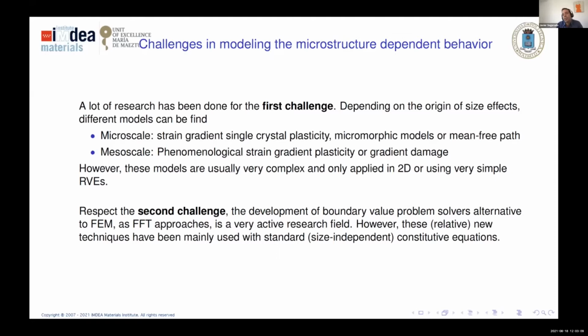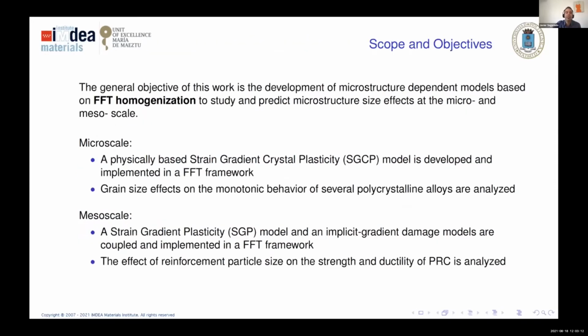And so the target is just to link the two challenges, and this is precisely the objective of this work. So we want to develop microstructure-dependent models based on FFT homogenization that allow us to study and predict microstructure size effect. I just want to emphasize what microstructure size effect means. Gradient models appear when the community wanted to see why specimens of a different size obtain a different response. So here the size effect is the relation between the specimen length, or some characteristic length of the specimen, with respect to some intrinsic length of the material.